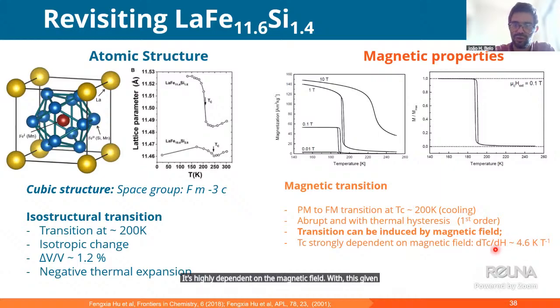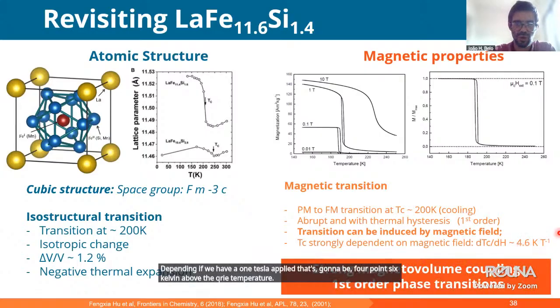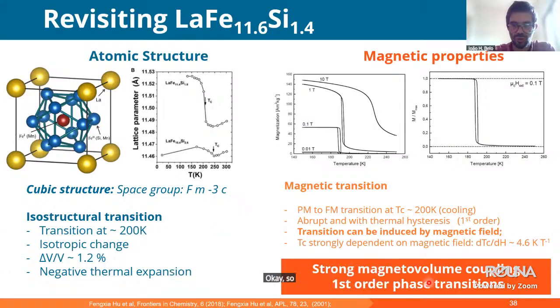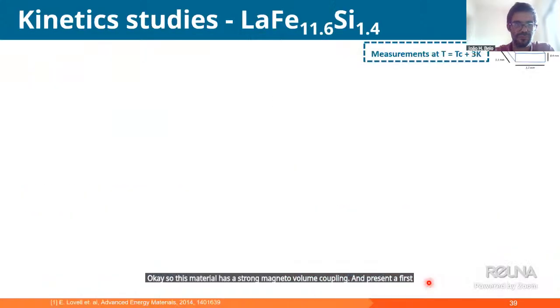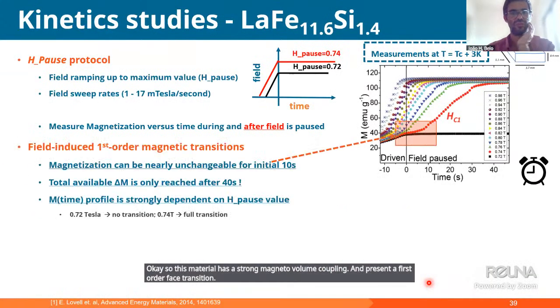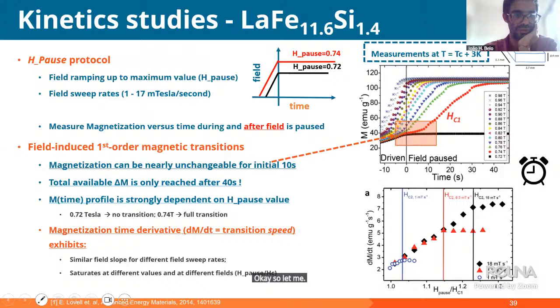So depending on whether we have 1 Tesla applied, that's going to be 4.6 Kelvin above the Curie temperature. So this material has a strong magneto-volume coupling and presents a first-order phase transition. Let me place it all here.